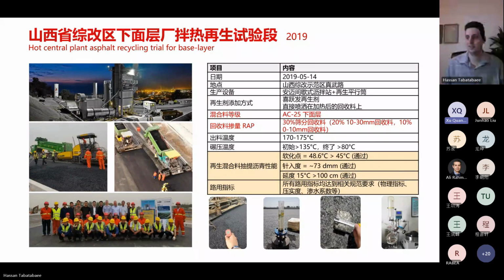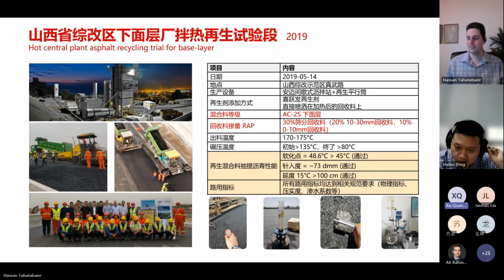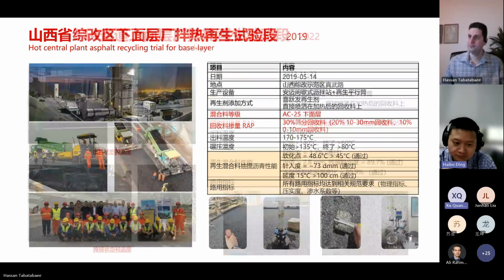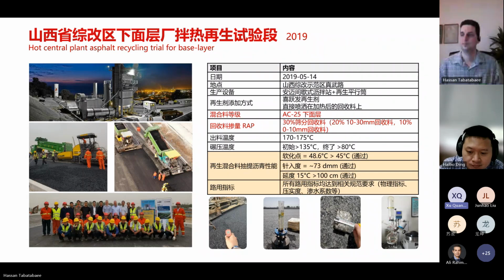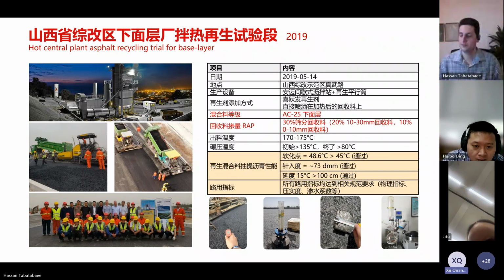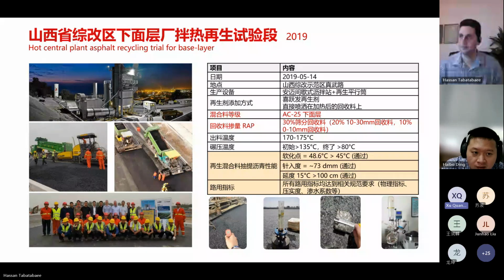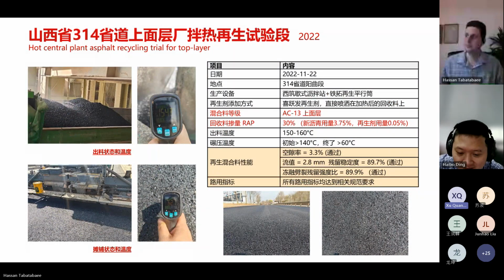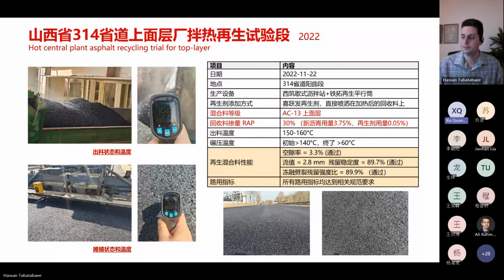Oh, perfect. Yes. I just got off the train, so just in time. Yes, starting from 2019, we have started to use ANNOVA rejuvenator in our asphalt mill. We have two asphalt mills here in Shanxi with recycling ability. One is with Ammann from Switzerland, and the other one is a Chinese mill. And we are also using this on the top layer recycling and using that in the top layer, because this is what we are trying to do, upcycling instead of the downcycling like we always do, to just use in the base or middle layer.